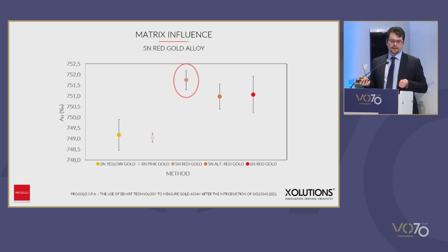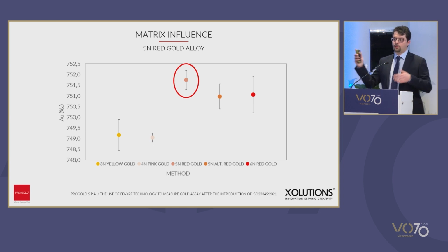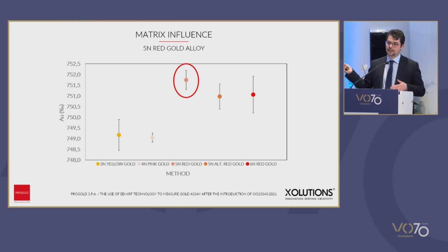And this is the result that we achieve. Above, you see the original measure, the calibrated method. It's in the red circle. And below, you see the results achieved by other methods. You see that in the case of alternative methods,